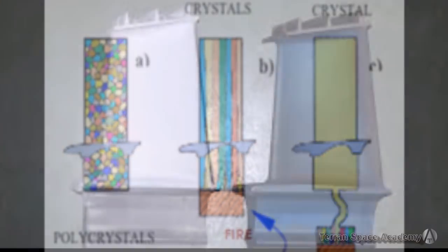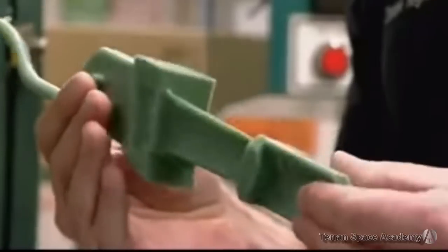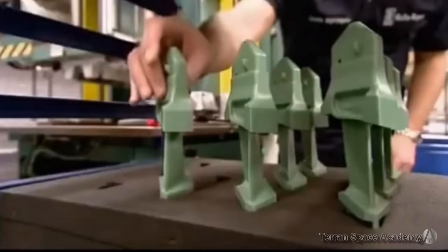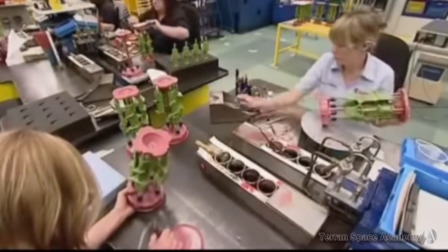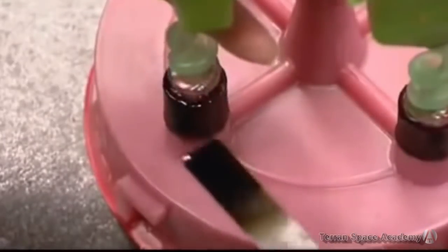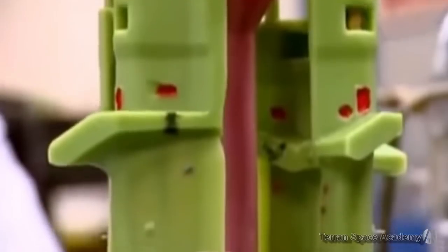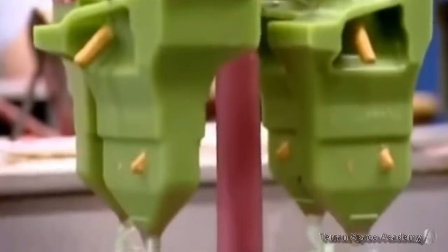The process to do this is extremely complicated. They first make a ceramic core that has the internal cooling channels in place. They inject wax to form the shape of the blade. Ceramic pins are inserted to support the core inside the wax. Then the form is coated with a mixture of aluminum silicate to form a ceramic coat. Several more coats are applied, and then the wax is melted out, leaving room for the alloy.